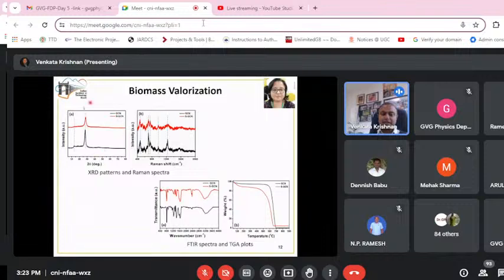One technique is X-ray diffraction, which indicates whether the material is crystalline or not, and where the peaks are coming. We can compare the peaks of this graphitic carbon nitride with those already reported in literature to get an idea about whether the material preparation is successful.